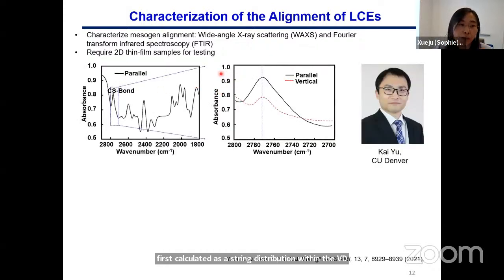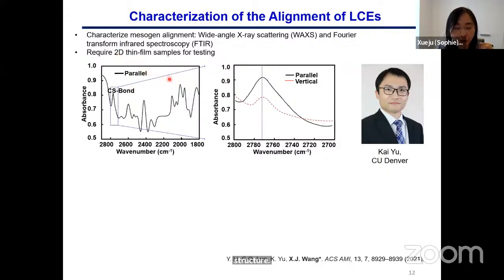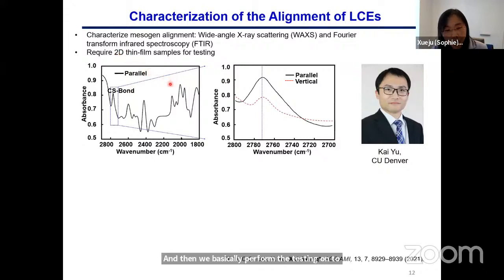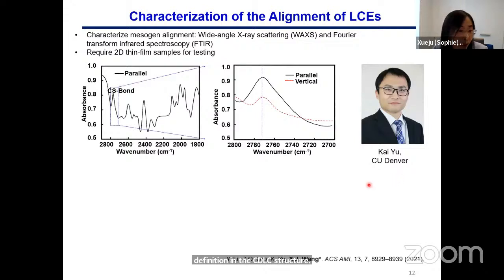So to estimate the mesogen alignment degree in the 3D structures, basically, what we did is we first calculated the strain distribution within the 3D structure, and then we basically performed the testing on 2D thin film samples corresponding to the strain levels. This way, we can basically estimate the strain-induced order deformation in the 3D LCE structure. Also, this testing is in collaboration with Professor Kai at CU Denver.